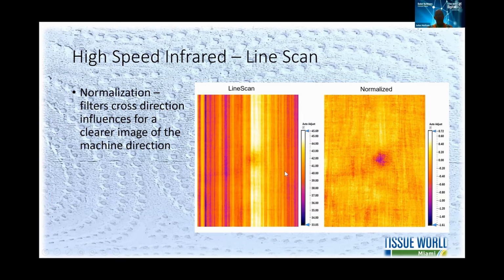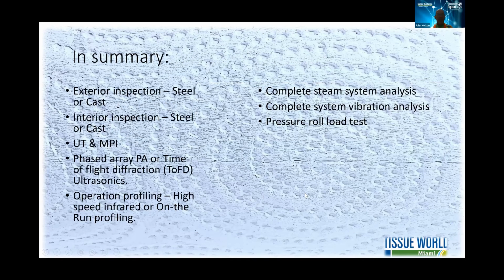In summary, exterior inspections can be on steel or cast iron dryers. The same with interior inspections. UT or MPI or magnetic particle can be used on both. Phased array and time of flight is typically an application for steel dryers to inspect the welds, etc. Operational profiling or on-the-run profiling looks for internal issues in the Yankee or upstream issues.